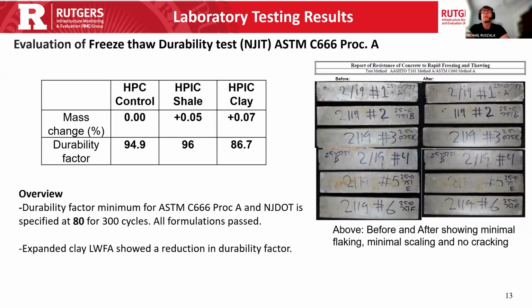So regarding freeze thaw, we tested the HPC control, HPIC with shale, and an HPIC with clay. We saw that the shale product performed very well. The clay product had a slight decrease. It still passed the test, which requires 80 durability factor for 300 cycles. So all formulations passed, but we did note that the clay product had a slight degradation with its durability factor.